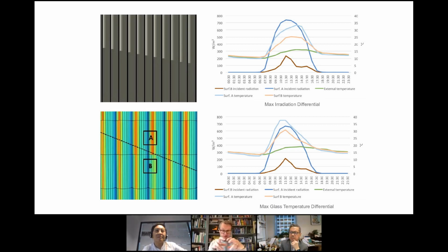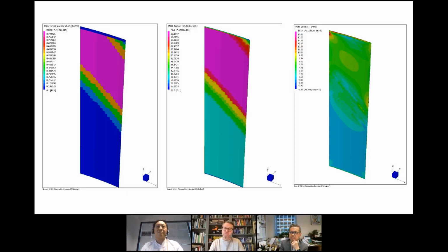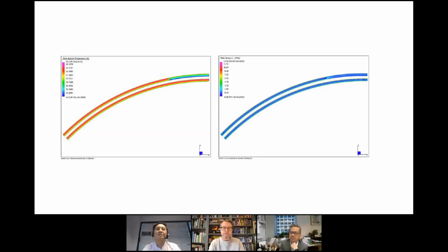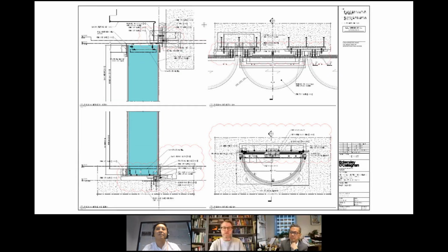But taking the combination of those two to get our worst case combinations of stresses, we can plot a gradient of that temperature across the depth, across the height of the glass tube or the glass panel, and we can then map onto that the ambient temperatures, and from that, through our finite element software, we can establish what the maximum stresses are. And in fact, you can see on the right hand side, we have a peak stress in the corner of the panel, which in this instance was below what would be an acceptable peak stress for annealed glass. So that process was very important in understanding how the glass would perform against heat. Similarly, the cross-section of the glass itself. So we were looking on the surface of the glass prior to that, but understanding through the depth of the glass how those stresses would build up relative to temperature.